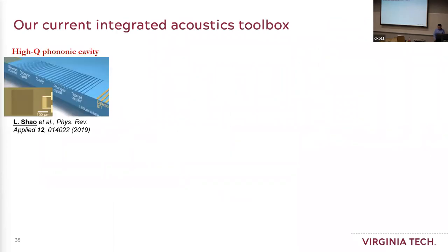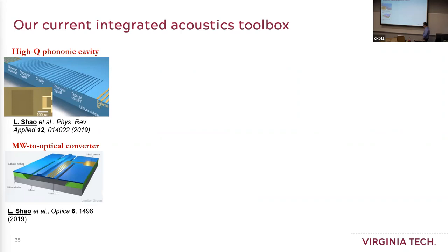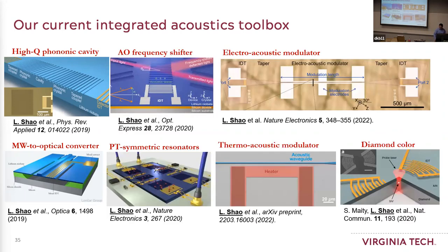The last thing I want to show you is my own reason for working in this acoustic field. We have already done several works. We started from how to make very good cavities on bulk acoustic wave substrates. We also studied microwave optical conversion using suspended structures. Later we thought, how about acoustic optic modulators, where the acoustic waves can modulate or bend the direction of the optical light? Then we thought we needed something non-reciprocal. So we built coupled acoustic cavities, then introduced gain and loss into the system to form a parity time symmetric system and enable non-reciprocal